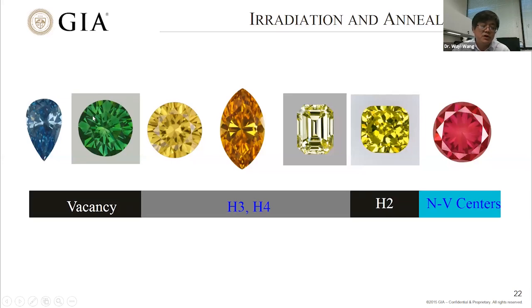If a diamond has some brown or yellow color, after the irradiation it will turn green. Basically, it is yellow plus blue, which means green color. These two stones at the left-hand side are irradiation only, without any annealing. But if a diamond, here we're talking basically about type Ia diamond, is heated up after irradiation, two types of defects, H3 and H4, will be introduced that can generate yellow, some orange or brown color. And sometimes, depending on the H3 defect, fluorescence can contribute to a green color.